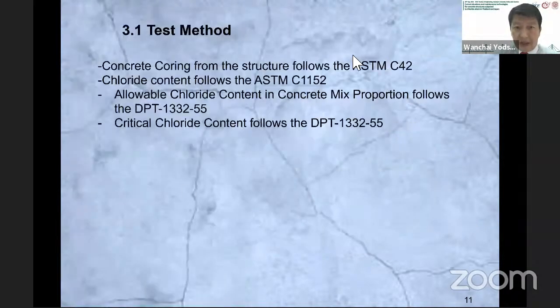For the test method of the chloride, we test the chloride content in the structure by using concrete coring from the structure. This is done following ASTM C42. And for the chloride content, we follow ASTM C1152. And for the allowable chloride content in concrete mixed proportion, we follow DPT 1332/55 that I already explained. And for the critical chloride content, we follow DPT 1332/55 also.